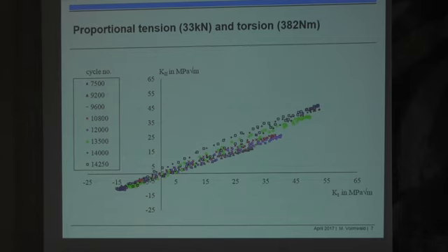There, no matter what load you apply, nominal forces or torsional moment, at the notch root you have a uniaxial stress state. And the crack initiates where the stresses are highest and grows first of all perpendicular to the notch root tangent line into the material, and therefore the start of all this is here with no K2, only K1, and K1 cycles here, maybe between -5 and 5 megapascals or something like that.